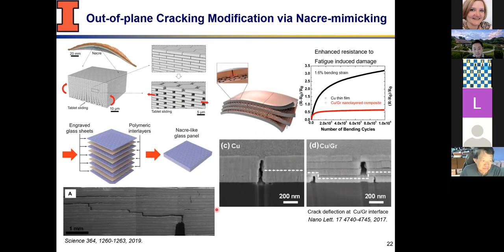So here are some cross-sectional views showing that cracks propagate through the out-of-plane direction, but not straight anymore because of the architectures that people put in and different strength of material or the soft-stiff combination that you put in there. So that's a very, very active research area where you could achieve very high toughness, high strength of the material by having these interesting architectures.